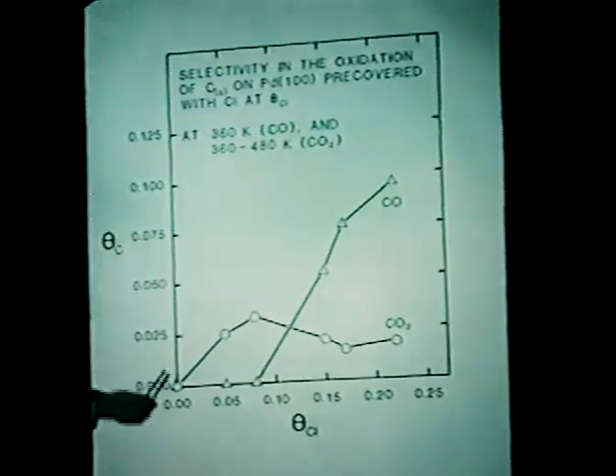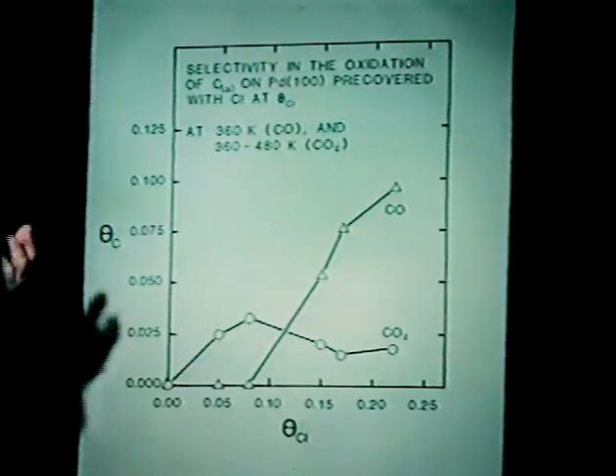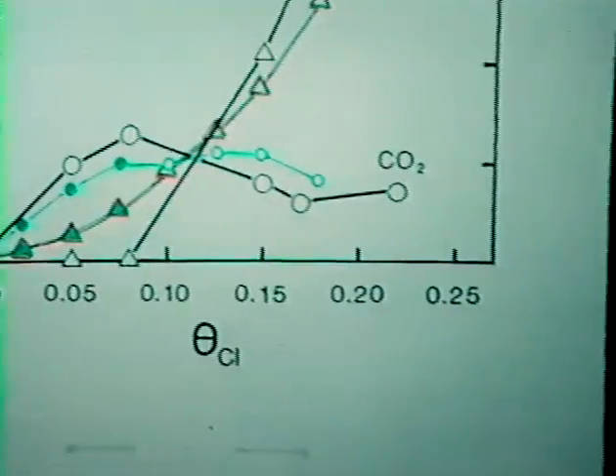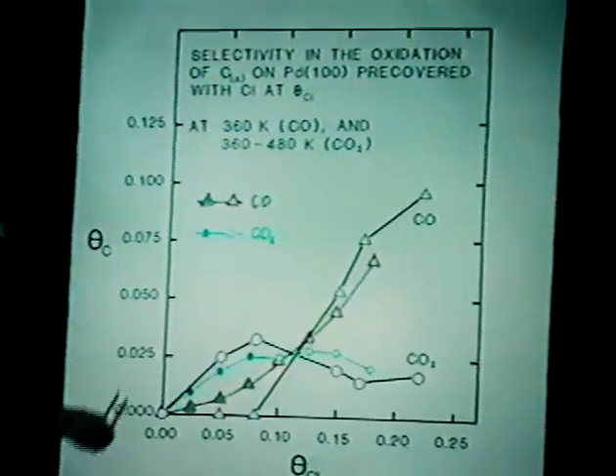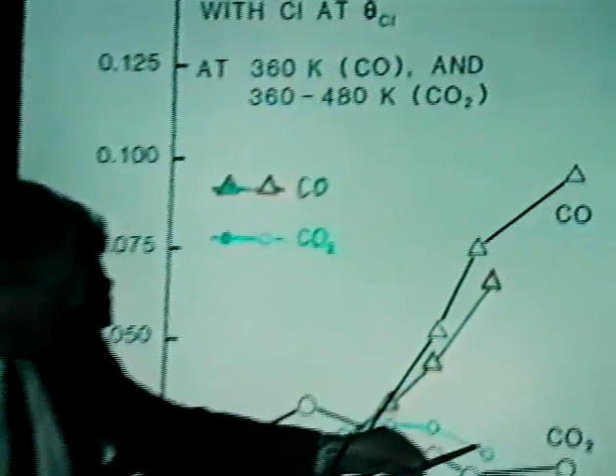But then where is the catalysis? Well, we remember we wanted to control the carbon monoxide, carbon dioxide ratio. The experimental finding is simply, as you would expect, as you increase the surface chlorine concentration, you are reducing the selectivity to CO2, and you're increasing the selectivity in favor of CO. Okay, so now how does the count work? It's not absolute, but the counting of the neighbors gave us this explanation of selectivity, taking into account all the other data, LEED data and so on, and this selectivity to CO2.